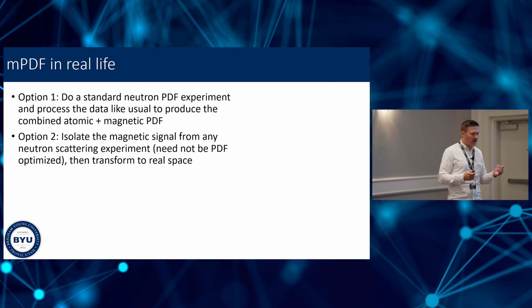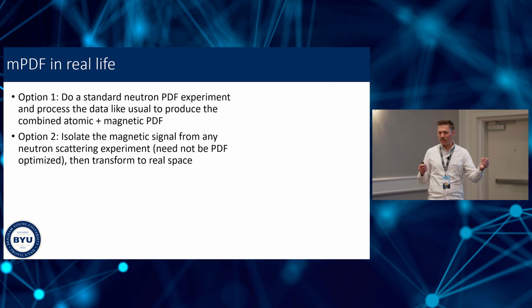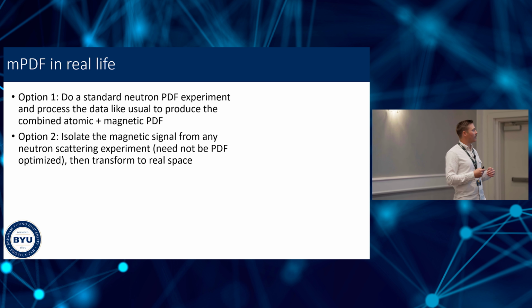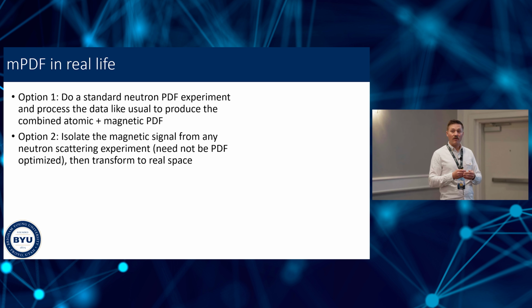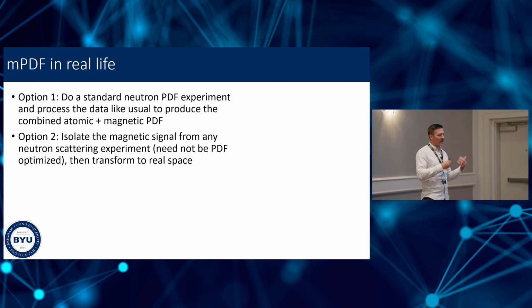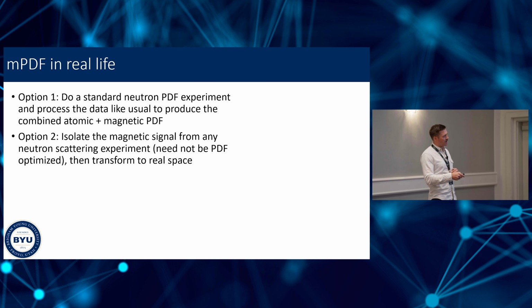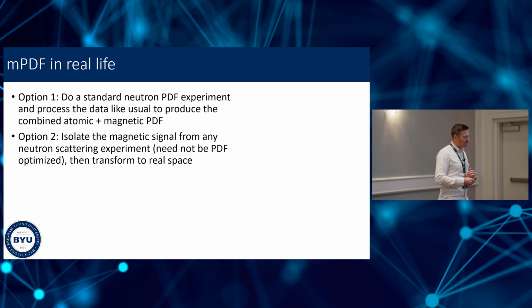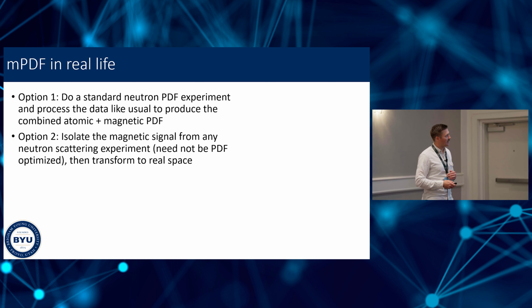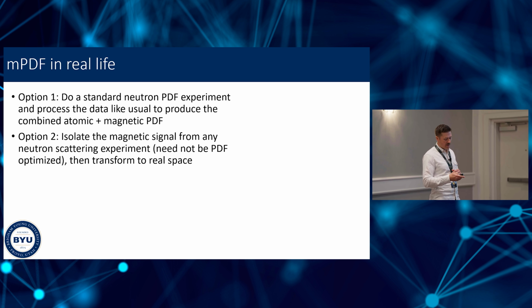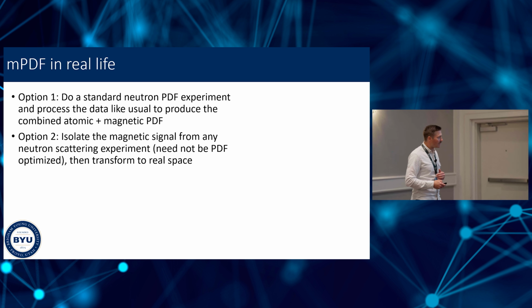Another way, you don't have to do a specialized PDF experiment, just any neutron scattering experiment. And then if you can find some way to isolate the magnetic component of the scattering, then you can Fourier transform that and get your magnetic PDF that way. Turns out that option 1 here has been used more frequently, and it works quite well actually. So for the PDF community, this is the easiest way to enter into magnetic PDF land.